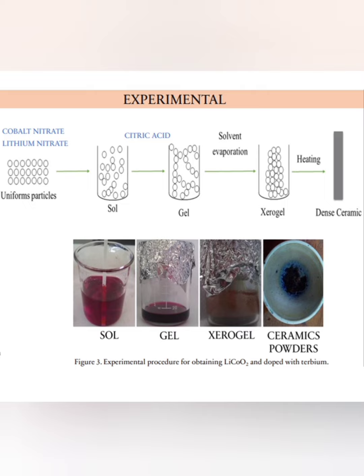There are several synthetic routes to obtain lithium cobaltate, such as solid-state, co-precipitation, hydrothermal, and sol-gel. The sol-gel route allows greater control of the hydrolysis and condensation, a pure and homogeneous product, nanometric particles, crystalline materials, and low thermal treatments. For these reasons, lithium cobaltate was synthesized and doped with terbium at low concentration by means of the sol-gel pathway.